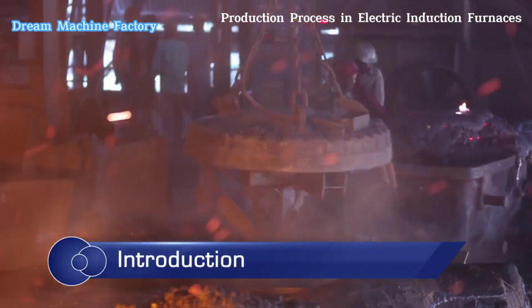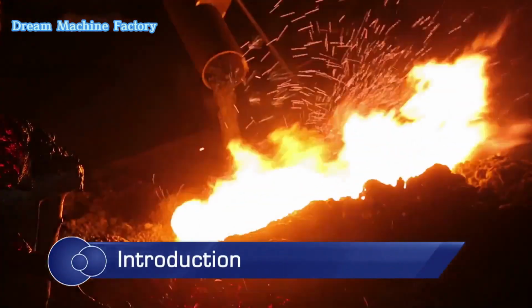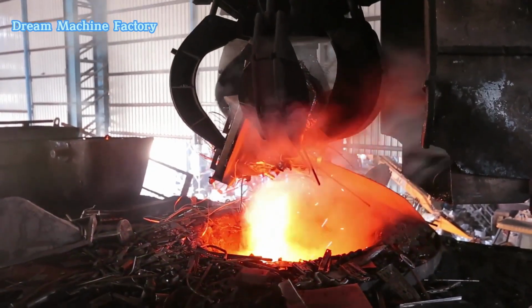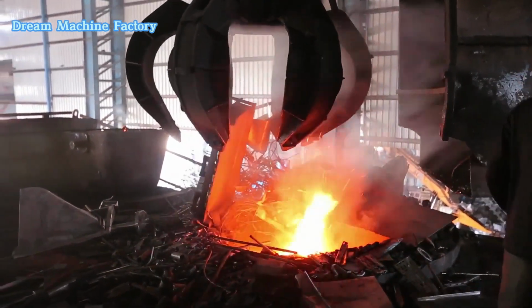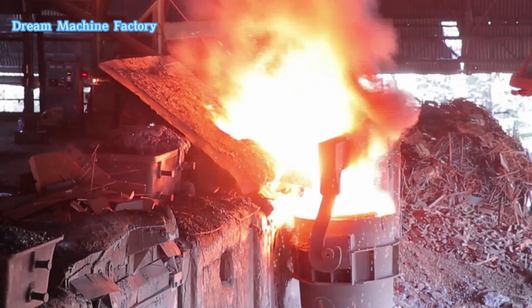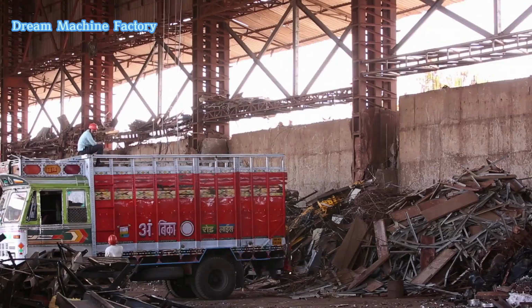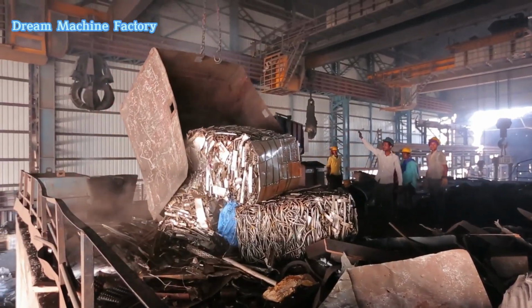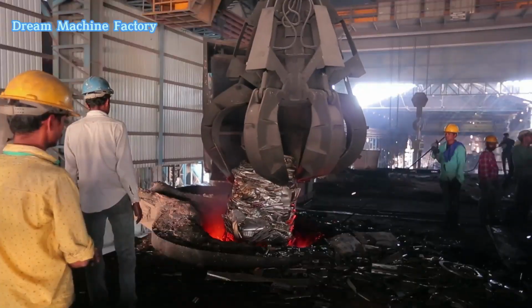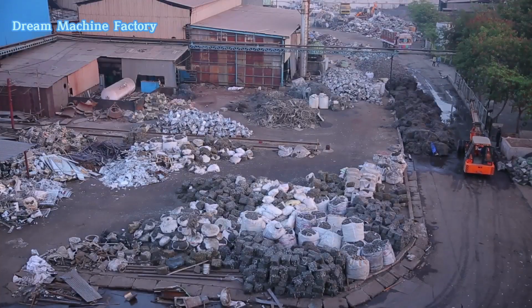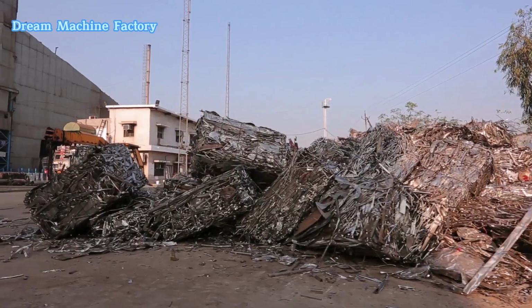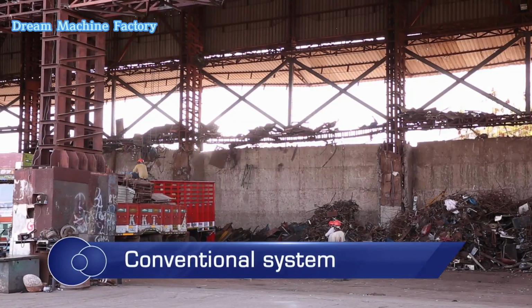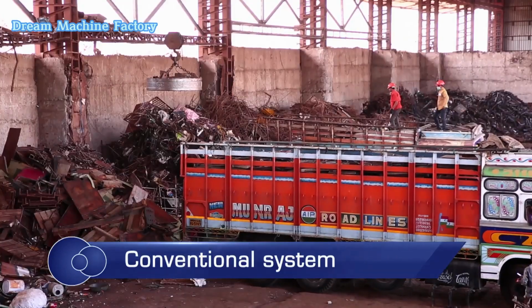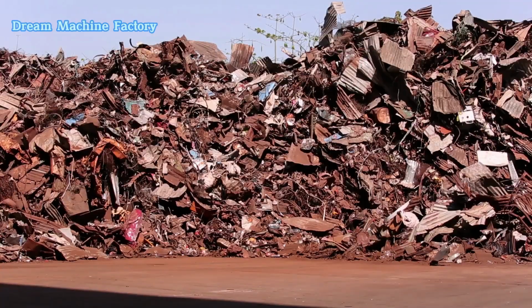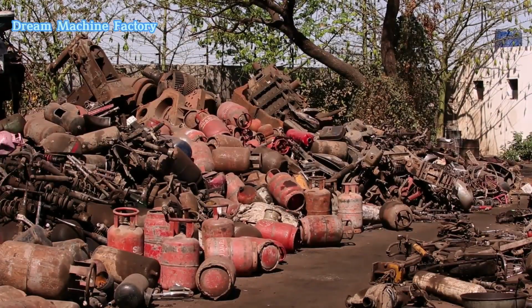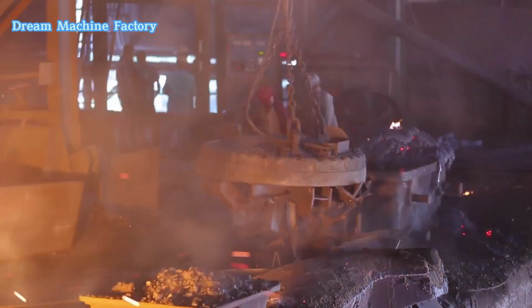Electric induction furnaces are widely used for melting scrap or sponge iron to produce steel ingots and billets. The process begins with feeding the raw material, primarily scrap or sponge iron, into the furnace. In India, especially in northern and western regions, scrap forms over 70% of the raw material. However, most induction furnace units use unprocessed or non-shredded scrap, leading to challenges such as low bulk density due to air pockets between scrap pieces. This results in inefficient power coupling, longer heat cycle times, and suboptimal furnace performance.